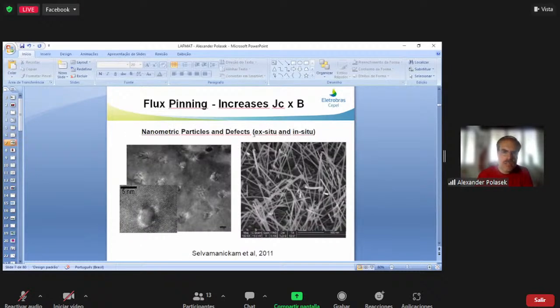And they can be introduced ex situ in your material or generated during the processing. And this is just a comparison of two kinds of morphology of particles. These particles are not superconducting, and so the flux will be trapped in these particles. A homogeneous distribution of particles with a suitable size is needed, and it is the main way of achieving high currents under high fields.